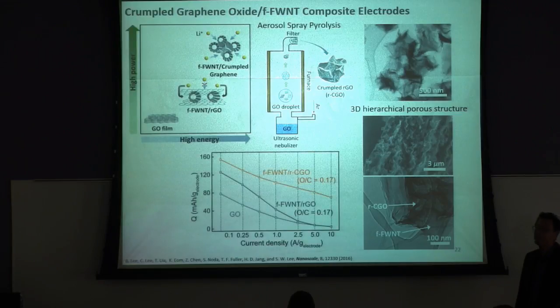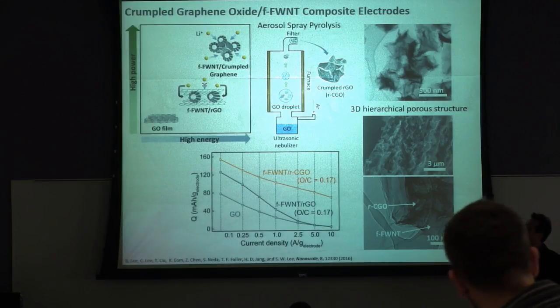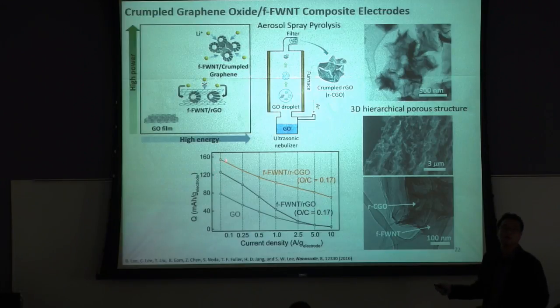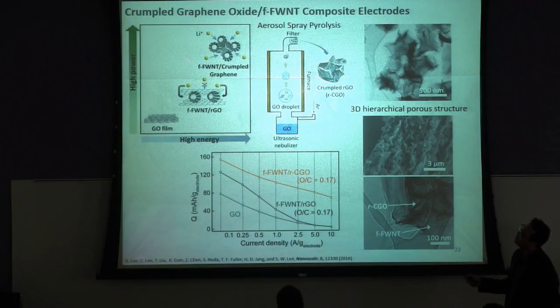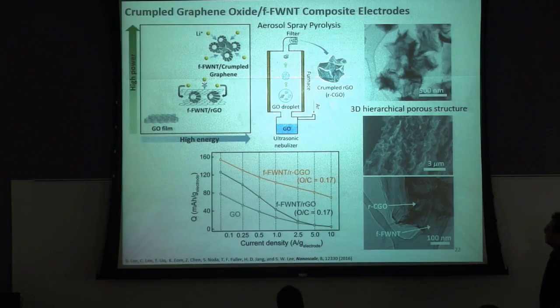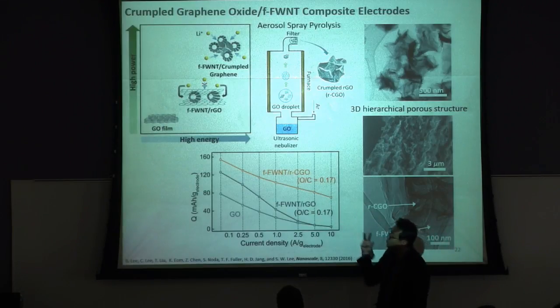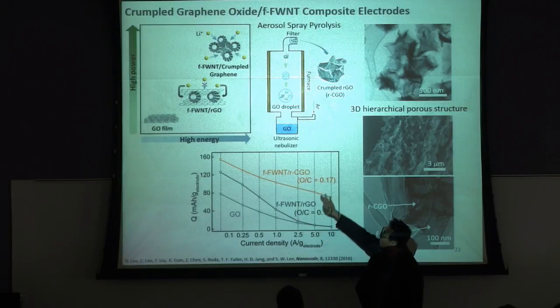So then if we compare performance, as you can see, the capacity has been increased. Now it's close to 160 milliampere hours per gram. Now if we see rate performance, we can see significantly improved rate performance compared to other graphene oxide and other composite materials. This is because of the facilitated electronic and ionic transport through this kind of hierarchically porous structure. It is interesting that these two electrodes have a similar chemical composition. If we compare the oxygen to carbon ratio, both have 0.17.